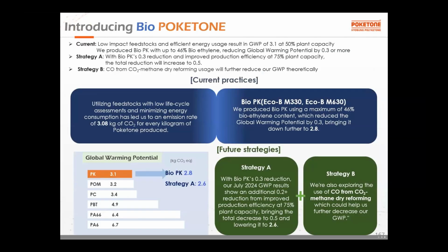And also we can reduce more of the GWP number because we are using the bioethylene. Used cooking oil based bioethylene. The 45 to 46% is comprised of the ethylene in polyketone. So we can reduce the GWP by 0.3. So the result will be 2.8. Also, if we increase the production efficiency to 75% of our production capacity, then we can reduce the number to 2.6. And last thing we should do is that we are also exploring the CO from CO2 methane dry reforming process. Will be helpful to further decrease our GWP value.